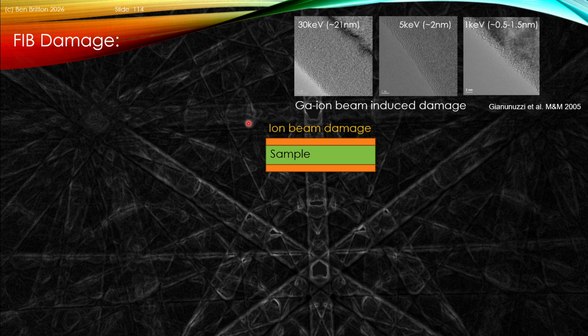We can also bear in mind that as we do the polishing steps, we have to be very careful to appreciate the consequences of FIB damage. So recall that the sample that we care about is very thin. Typically it'll be less than 100 nanometers total foil thickness, but now we might have a surface layer, and if we're at 30 kV, we could have a 100 nanometer thick foil that has 20 nanometers of damage on either side, because we haven't polished or developed a strategy properly. If we get this down to 1 kV with gallium, we can get something like 1.5 nanometers, which then gives you like 4% if this was 100 nanometers thick. So 4 nanometers or so would be damaged, 2 nanometers on either side, so 4% of this.